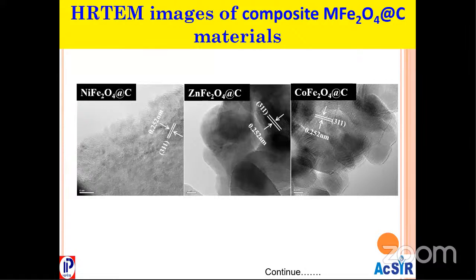The presence of spinel structure was confirmed by TEM images, where we can see the d-spacing, which we can also learn from XRD spectra, right? MSc students can calculate how to get it from Miller indices. You will get the d-spacing and what the plane is, right? So this was confirmed by TEM images, that the d-spacing of 0.25 nanometer was visible in all cases. So we can say that the spinel structure of MFe2O4 on carbon was confirmed.